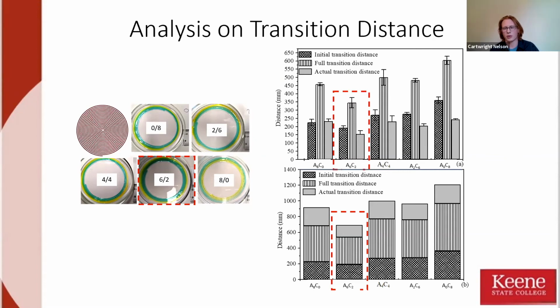And then once it got more and more viscous towards the completely CMC material, it was too viscous, so it required more pressure to print at the same volume by speed, and that just slowed down the transition because there was less material leaving the nozzle at the same speed, so it increased that distance.